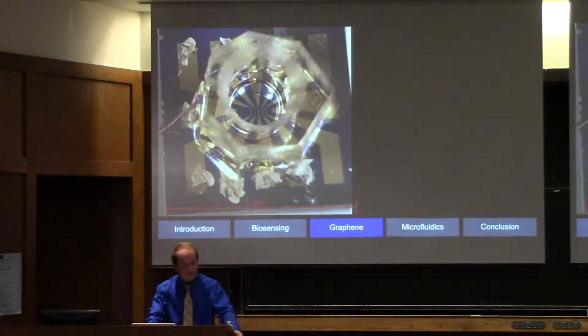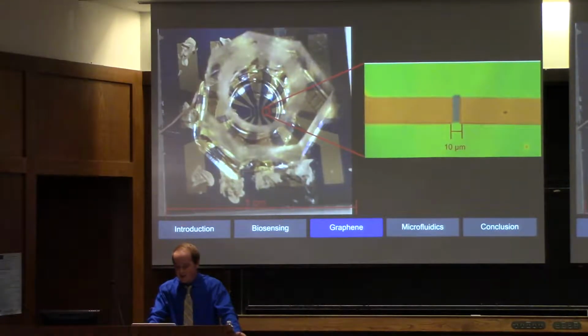This picture here on the left shows what one of our current biosensing devices looks like. The gold pads serve as contact points that allow us to measure the resistance across the graphene. And the graphene actually sits in between each of these pairs of contact points. The surface area of the graphene itself is incredibly small. It's actually only 10 micrometers in width.